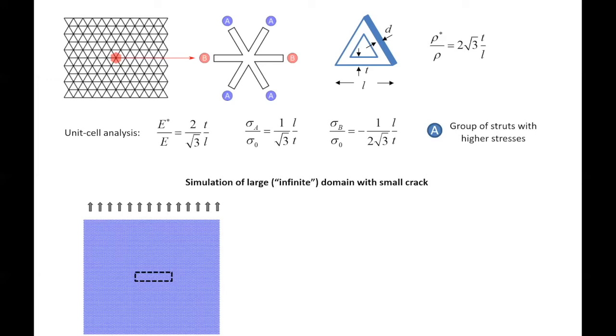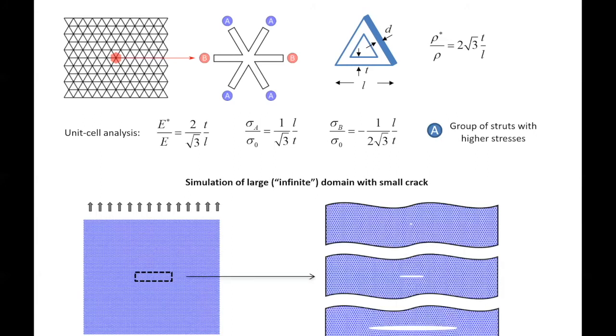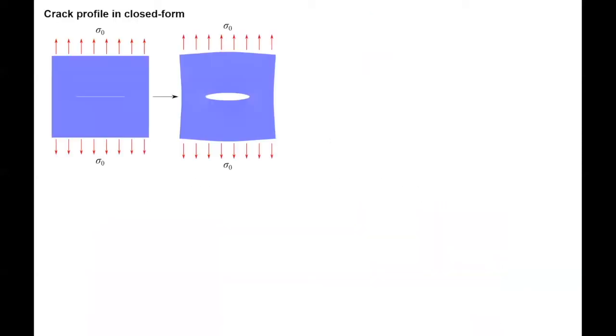And we say, okay, let's pull. Every time we reach some stress, we remove one strut. Let's see how that looks. And what you see basically is that the triangular lattice will behave as you would expect. It's going to grow horizontally. So now that we do have a path orientation and propagation, we want to find the energy